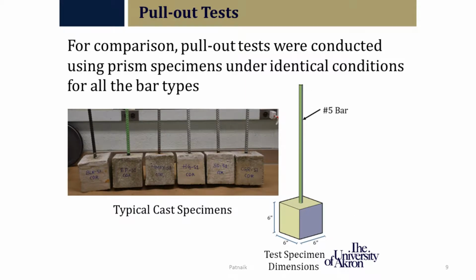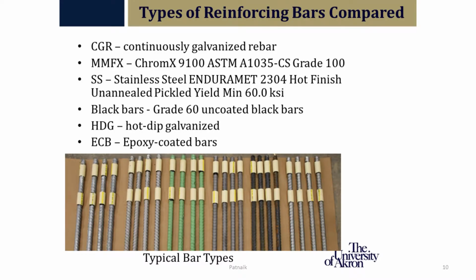You can see this particular test, this first set of tests, is a little 6x6x6 cube with the different types of reinforcements in there. Prism specimens under identical conditions for all types of the bars. These are pictures of the bars that were laid out prior to casting them, but you have continuous galvanized rebar, MMFX 9100, stainless steel 2304 at a 60 KSI, uncoated, traditionally hot dip galvanized, and epoxy coated, and they're all provided by industry partners from the University of Akron.